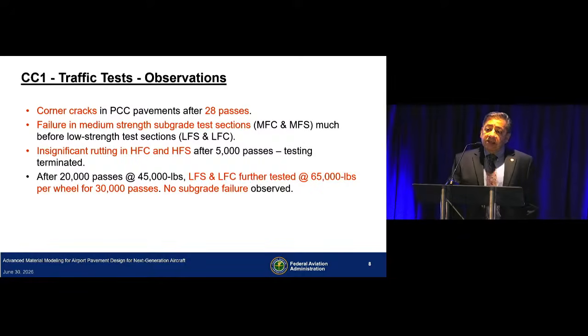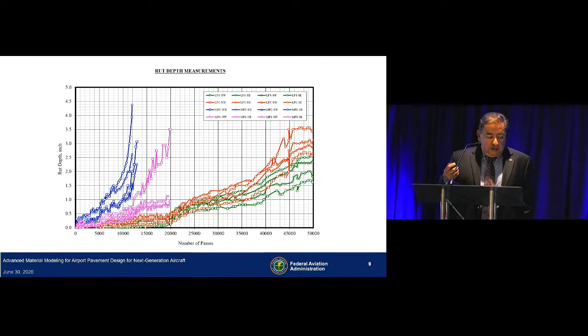After 20,000 passes at 45,000 pound wheel load on the low-strength sections, we increased the wheel load to 65,000 pounds. That's a significant increase in the wheel load. And we put on an additional 30,000 passes, and still those sections did not show any signs of subgrade failure. On this figure, you can see the rutting results. These are the medium-strength sections that failed right around 10,000 passes. This is the medium-strength section with stabilized base, and these are the low-strength subgrade. Right here is where we increased the wheel load to 65,000 pounds.